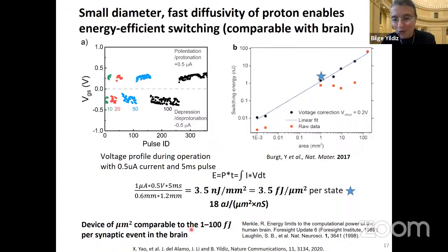So now if we compare that to the energy consumption per synaptic event in our biological synapses, that's on the order of a few to 100 femtojoules. And even though we are dealing with this rather non-optimized device, if you are working with a micrometer device, the energy consumption becomes comparable to the biological synapse energy consumption. So this has motivated us really a lot, and there is really a promising path here to run such inorganic devices with very, very low energy consumption when we are emulating the electrical properties of synapses. So a few femtojoules, comparable to the biological synapses in the human brain.